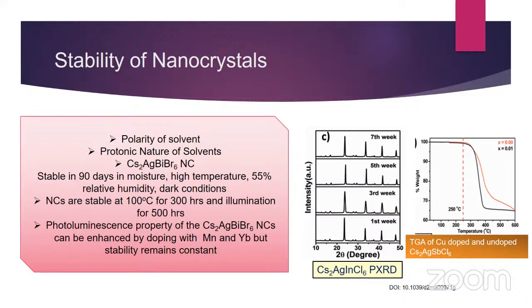And there is one also interesting result which I have mentioned here. For the Cs2AgBiBr6 nanocrystal, you can increase their photoluminescence property by doping them with Mn, but still their stability remains constant. So this doping does not affect the stability. So in this diagram, I have shown the powder XRD of Cs2AgInCl6 material. Here you can see the XRD patterns remain the same up to 7 weeks. So you can see here the peak positions, they are not changed.